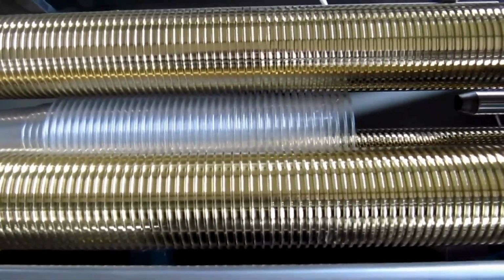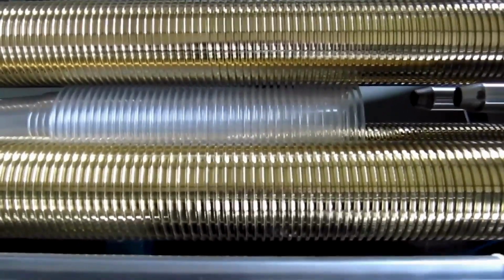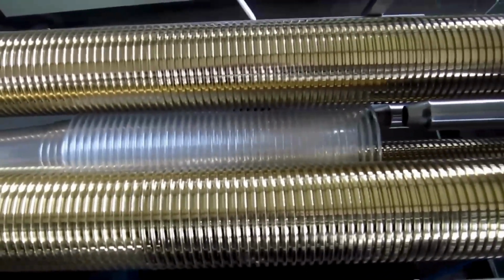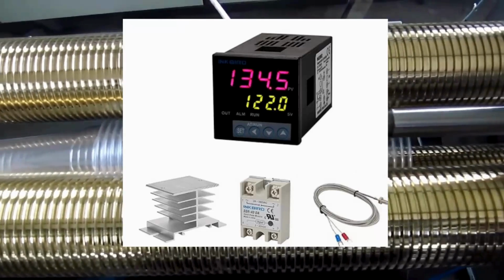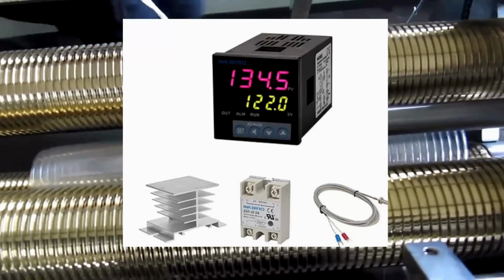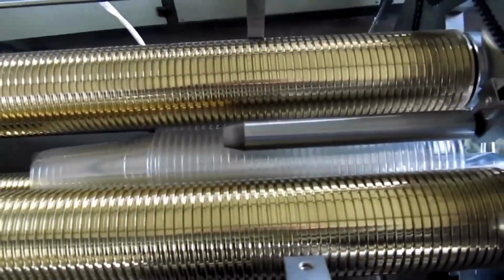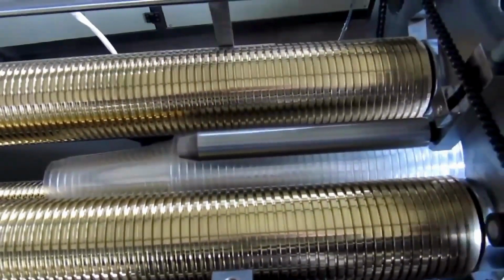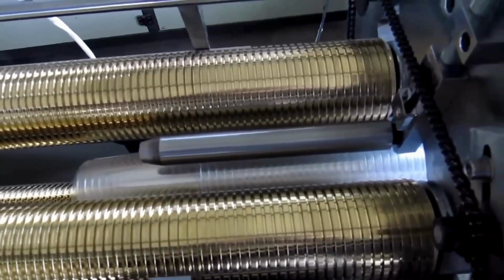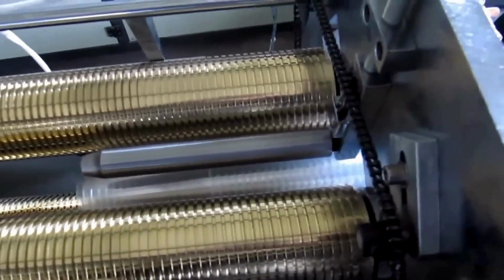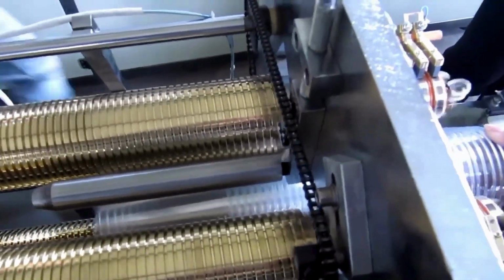Temperature control here is critical. Too cool and the rim cracks, too hot and it loses shape. That's why modern systems use PID-controlled heaters to keep the temperature within just a few degrees of Tg. After rolling, the cup is cooled again using forced air or chilled mandrels to lock in the final shape.